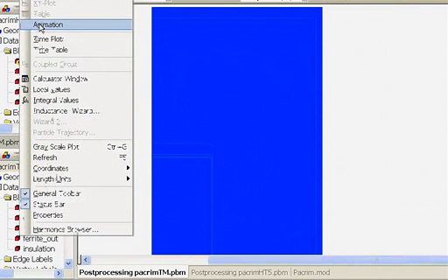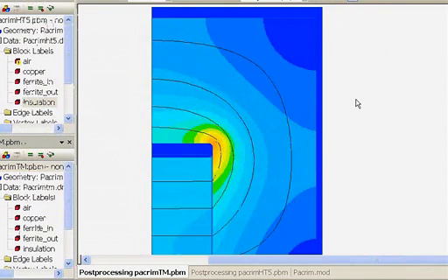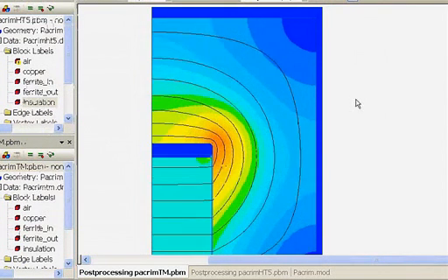It will make a graph in a fast time, so we can actually see the rise and fall of flux density around a sine wave. So it's rising now. The red is approximately 0.4 tesla, which is well into saturation in the ferrite. See, it's saturating in the corner. As we all know, that's where our cores get hot, on an internal corner.